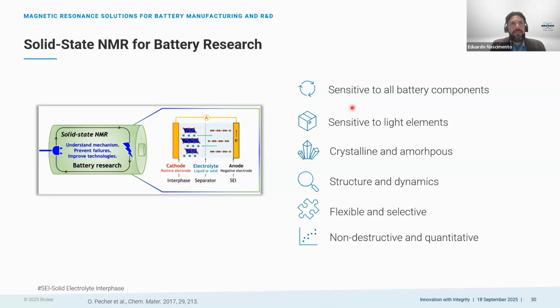NMR is sensitive to light elements, something that X-ray is not. So especially for lithium analysis, solid state NMR is very unique in that sense. We can also analyze crystalline and amorphous samples, something that XRD cannot do. So NMR can provide structure and dynamic information, and is a very flexible, selective and non-destructive method.